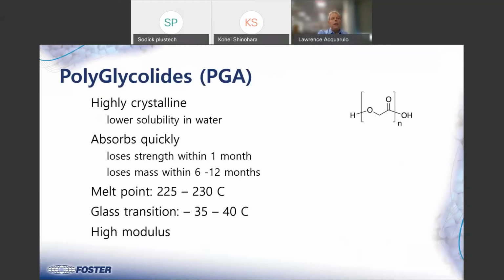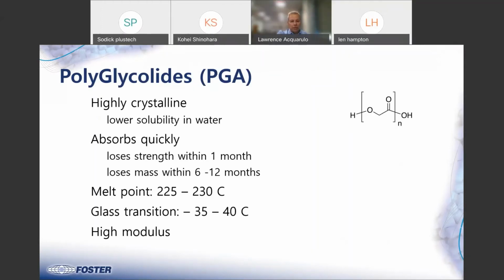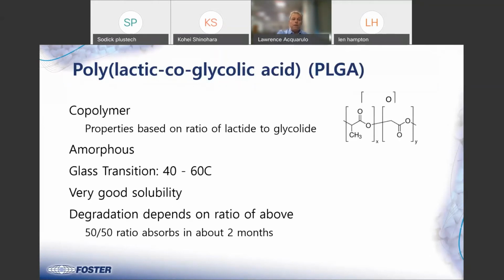Polyglycolides: highly crystalline, lower solubility in water. Now this polymer absorbs a lot quicker, 1 month. So you probably wouldn't want to use it in an orthopedic application where you require the polymer to pick up some of the strength of the bone if the bone is healing. So that's something to take into consideration. And it loses most of its mass, almost all of its mass, in 6 to 12 months. So this is something that does resorb a lot quicker. Higher melting point, lower glass transition temperature, and again, high modulus.